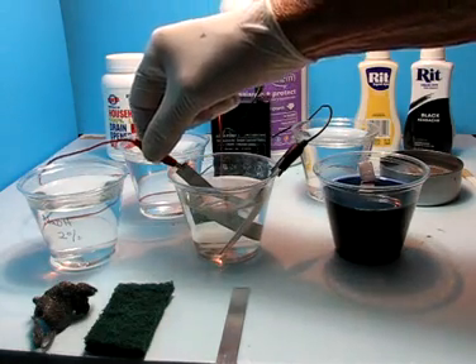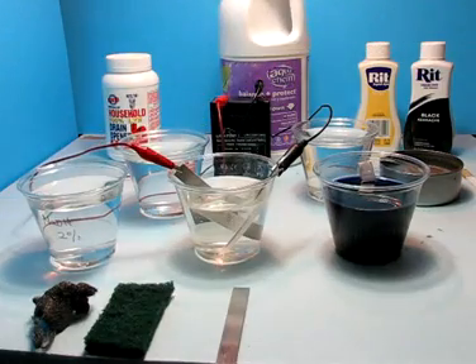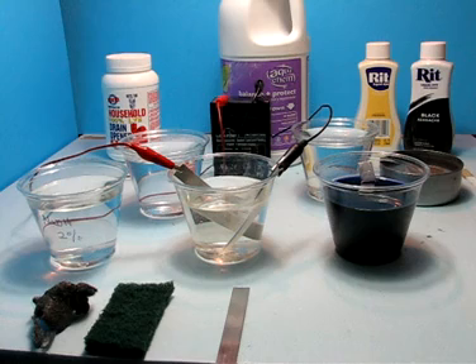The anode is obviously the positive side. There is a slight change in the metal when it is done, though it is very difficult to show visually. I would suggest starting with a 20% solution of sodium bisulfate as recommended in the write-up after this video. Give it 60 minutes and then take a look — the cell structure generally shows up very nicely with a slight yellow tinge.